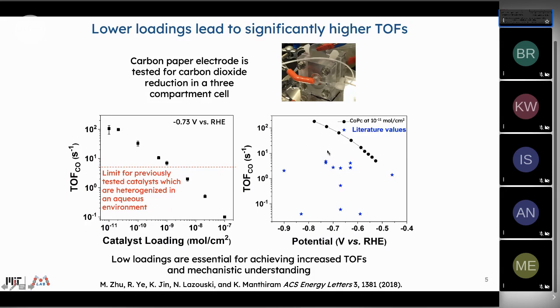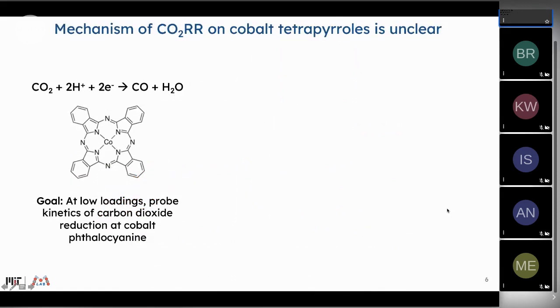One can look at this finding of turnover frequency at not just one potential, shown here at minus 0.73 volts, but at a wider range of potentials. I think this is important just to get a sense of how this catalyst behaves as a function of potential. And you'll see that relative to the highest turnover frequencies that have been previously reported in the literature, this low loading, high dispersion limit does in fact lead to higher turnover frequencies at a wider range of potentials. This is very important for trying to kinetically probe this catalyst. One needs a catalyst which is not transport limited in order to understand the mechanism by which it conducts that reaction without convolution from transport. So that is what's enabling of this sort of dispersion method.